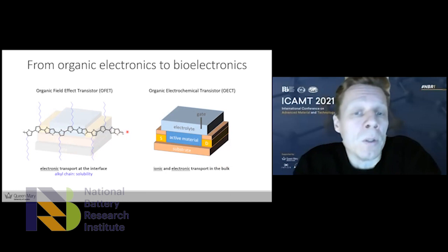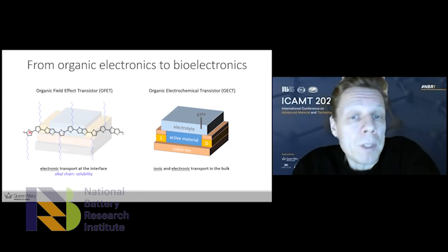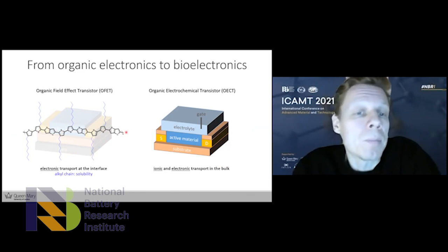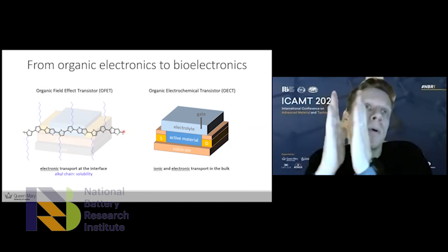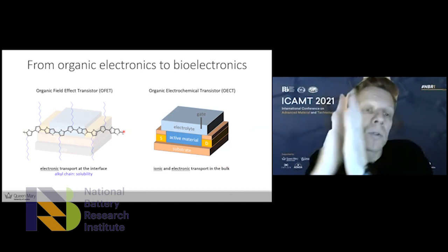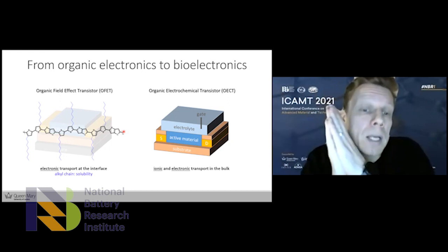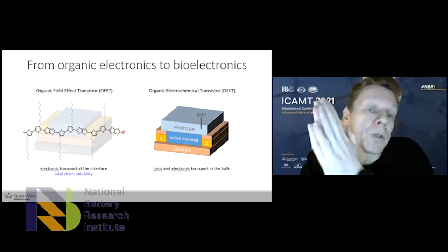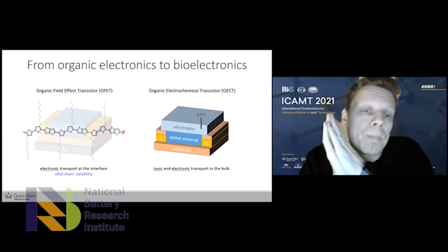So if we look at a typical field effect transistor material, it can be these types of polythiophene here, where we have a conjugated backbone that can delocalize pi electrons, meaning that we can inject charges, either positive charges, electron holes, or negative charges, electrons, into the material, and then we have efficient charge transport along the polymer backbone, and we have efficient charge transport when the polymer chains pack together, so charges can also hop from one polymer chain to the next. So these types of materials are very good for electronic transport at the interface.